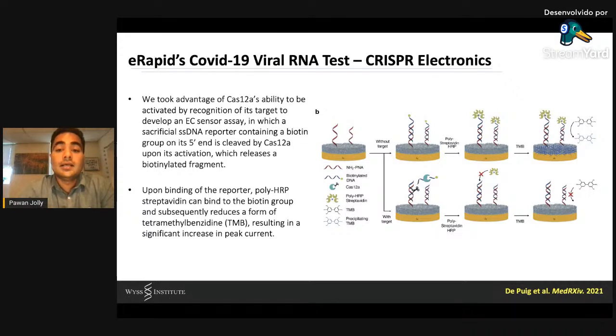So in our case, if you don't have the target, all the reporter DNA will bind to our surface, which was modified with PNA. PNA is peptide nucleic acid. The reason we used this was to enhance the binding and also so that this sensor can be used in different conditions, different ionic strengths.